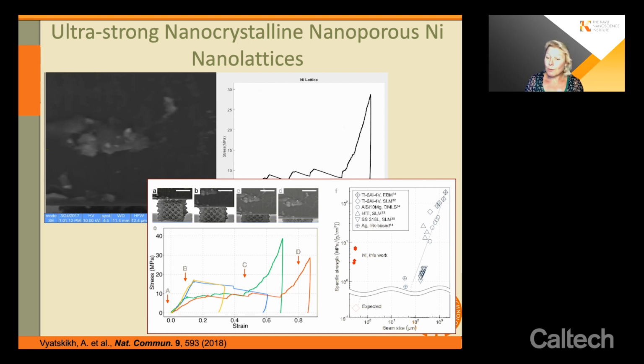So what we would like to point out is that the very, very low quality nickel material that we're presenting here, that's nanocrystalline and nanoporous, fares so well that its strength, we had to break the plot. So its strength is equivalent to something that would have the dimensions of about 0.5 millimeter. So it turns out that the nanoscale is actually quite forgiving against defects, and you don't have to sacrifice your mechanical resilience.